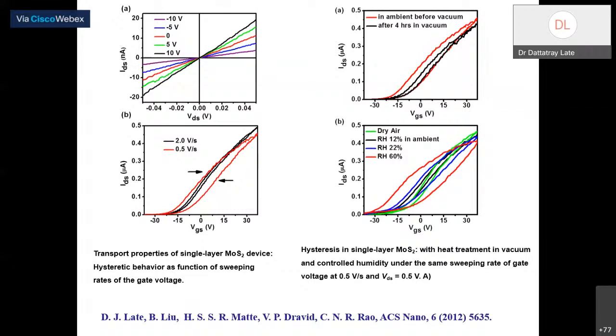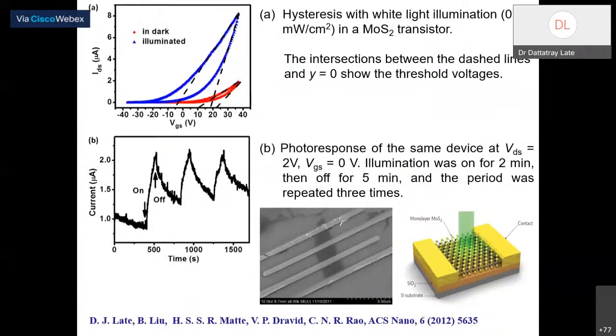Okay, we have done experiments with various humidity levels. You can see the water level is 60%, 22%, 12%, and dry air. How the hysteresis has slightly become smaller and smaller, right? We also did an experiment with the dark condition and photo condition, and I found that this is also one of the reasons for hysteresis.